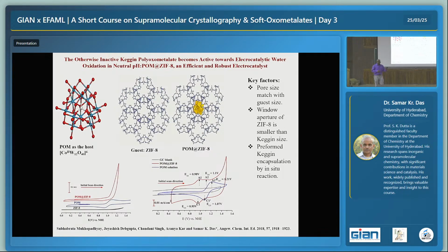Now let me tell you, we don't have control of the encapsulation. Control means we cannot say that I want all cages to be filled. No. Whatever way we did, we always found that one cluster goes in 7 cages. We have kept less amount and more amount, but if we put very little, we cannot get all filled. Generally, we get one cluster per 7 cages. That we characterized. We don't get a single crystal for this one; we always got a microcrystalline compound, with PXRD and other characteristic properties. We proved that this compound got encapsulated with one cluster per 7 cages.